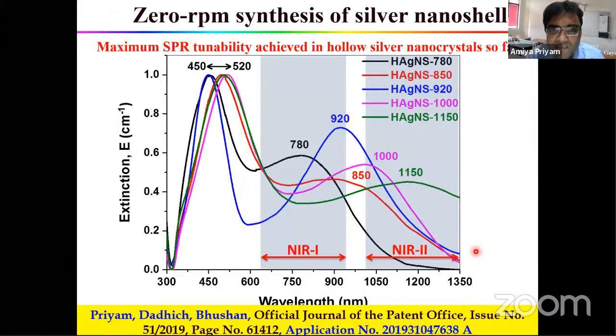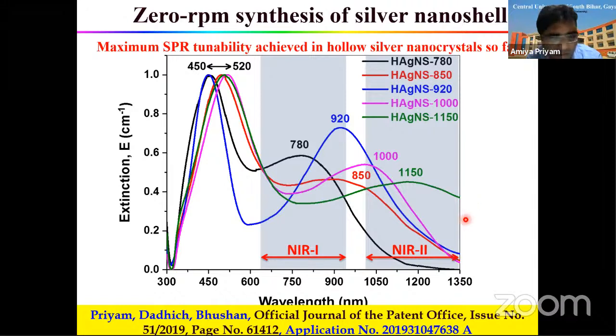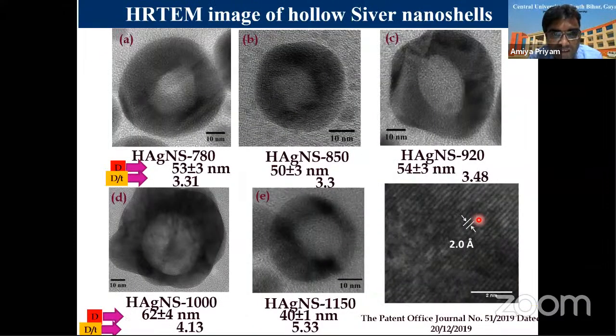By adjusting a few parameters more critically, we were able to further tune it beyond 1000 nanometers. You can see the maximum tunability we could achieve was 1150 nanometers, and we are not able to take the spectrum on this side because at around 1400 the water starts absorbing. That is a problem. We are trying to fix that and will be trying further. The NIR-3 window is still unexplored, and that is something that we will be doing. So these are the results, as they say, seeing is believing.